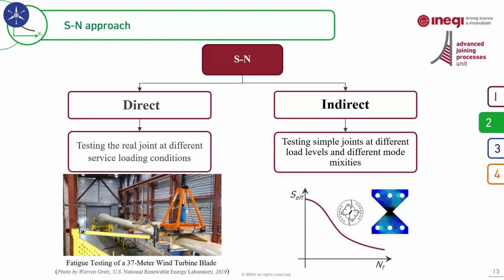But the very good point here is that in this indirect approach, we characterize the adhesive. It means that the results can be used for a wide range of structures, joint geometries, and loading conditions. And we need to be very careful here, because in the indirect methodology, we estimate the fatigue life and do not obtain the real fatigue life. But in the direct methodology, we obtain the real fatigue life.